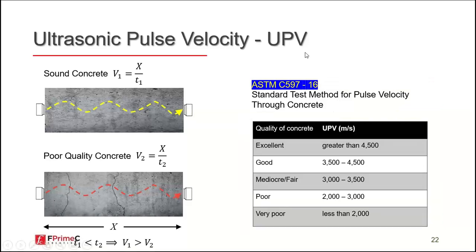We can use codes like ASTM C597, last updated in 2016, to help engineers assess ultrasonic pulse velocity in concrete. This can be done on concrete cylinders, the most ideal scenario, or in the field using direct and indirect methods. When you have excellent quality concrete, you expect wave velocities around 4,500 meters per second; poor quality concrete produces velocities of about 2,000 to 3,000 meters per second. Different tables and benchmarks have been developed over the years, and you can use the ones most appropriate for your type of facility.